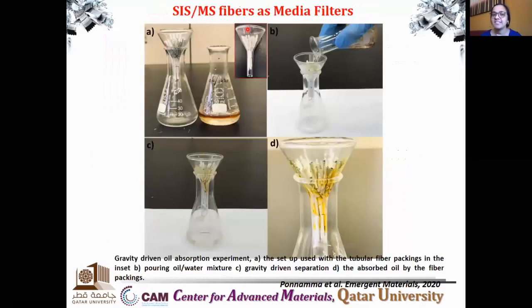Here we also tried the SIS mesoporous silica as media filters. In the beginning, when we did the electrospinning, the fibers were just stuck on the aluminium foil. So we thought, why don't we roll this aluminium foil into small cylinders and pack the cylinders in a conical flask like this? And we were successful. We added some oil water mixture like this, and it was quite amazing to notice that all the oil molecules were absorbed by these cylinders. So we also proposed the possibility of using the same composite as media filters.